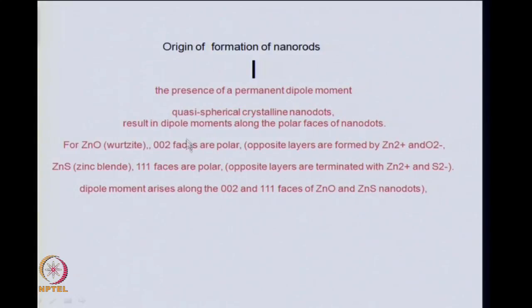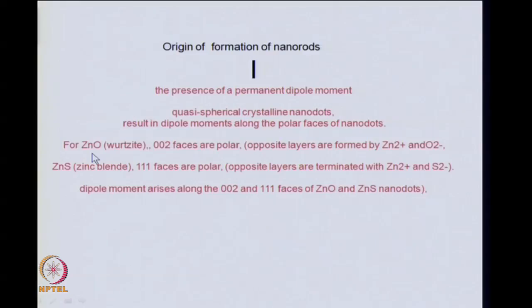Now, whenever you have this dipole moment, so there is some positive and negative type of charges on opposite faces or opposite layers, then the fresh ions, which are say positively charged ions, will come closer to the negatively charged faces, and the negatively charged ions will come closer to the positively charged faces. So if you look at zinc oxide, for example, the wurtzite structure of zinc oxide, in that the 002 faces